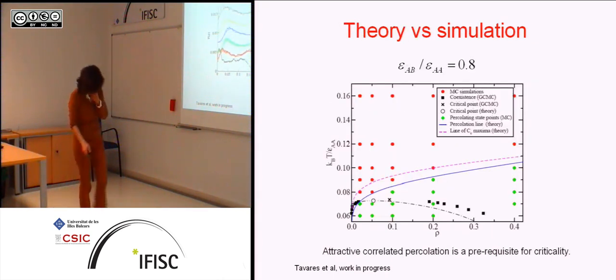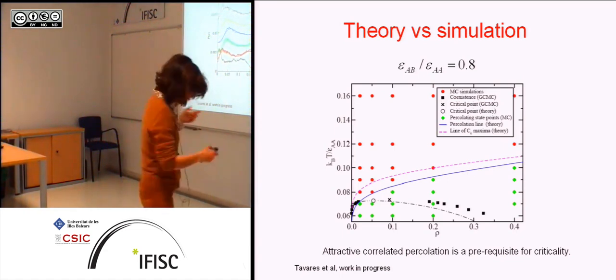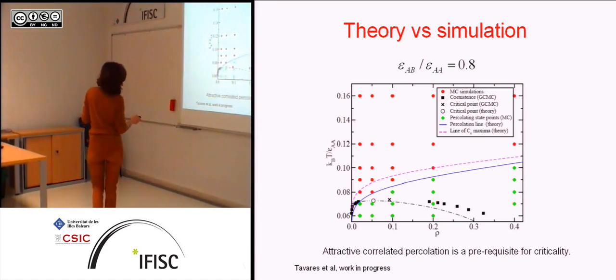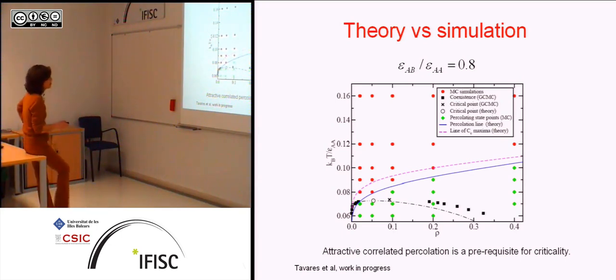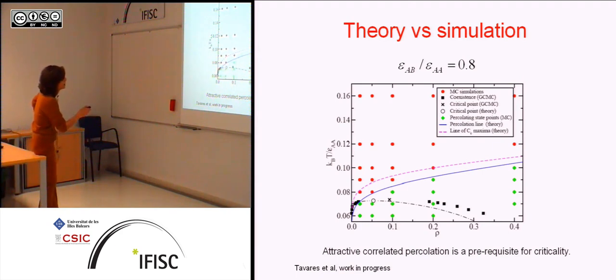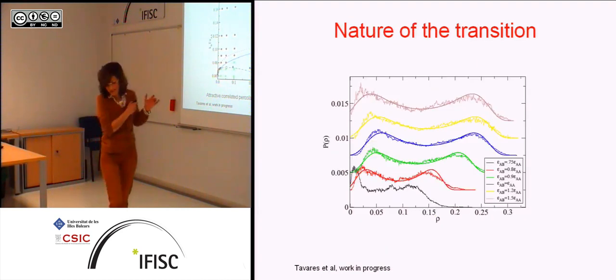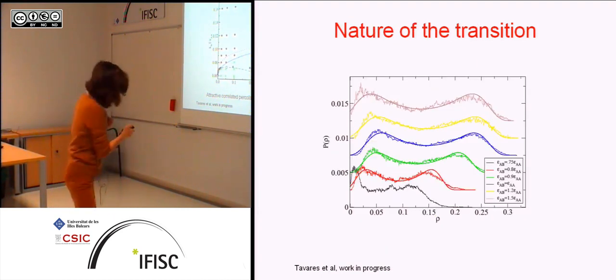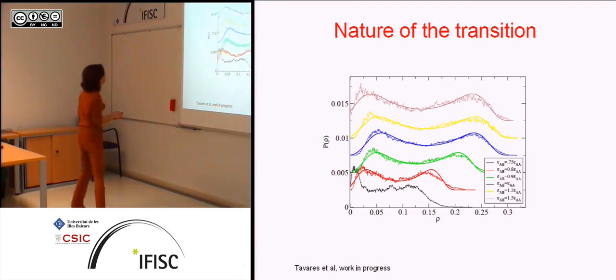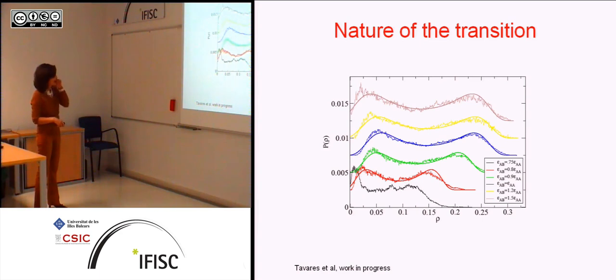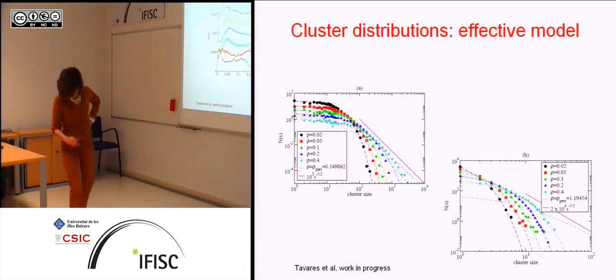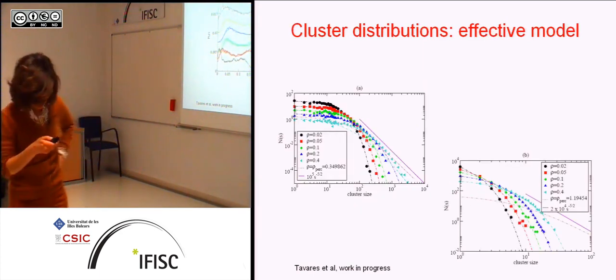Okay, now this is the final point, and we have a phase transition if I go back. So this is a normal condensation transition, we think, but that's what we have to figure out. We have a percolation here. This scale for these parameters is still, these points are quite separated. But what happens if I start lowering these quantities, the critical point will go to the left, and the percolation line cannot go maybe density, so these two points will approach, and this is work in progress, so we're trying to figure out if this transition is still Ising-like, and it seems that it's Ising-like for most points. We have a point here which seems to be quite different.